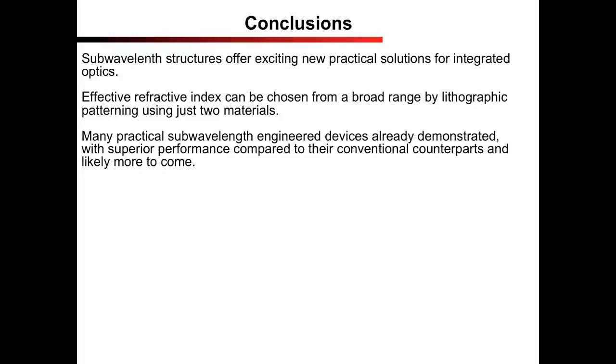I would say the message to take home from this short webinar is that subwavelength structures offer exciting new practical solutions for integrated optics. The key point is that the effective refractive index can be chosen from a broad range of values by lithographic patterning using just two materials, for example silicon and silicon dioxide.